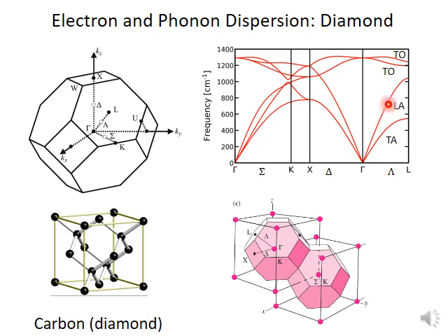Now coming to what branches there are. If you look at phonon waves which move in the 1-1-1 direction, this wave has a longitudinal acoustic branch and a transverse acoustic branch, and the transverse acoustic branch has only one branch. It would mean that the two transverse branches are degenerate. In other words, if a wave moves in the 1-1-1 direction, the transverse spring constants are exactly the same in the two transverse directions. Similarly, the optical branch has an LO branch and a TO branch. So again the two transverse branches are degenerate over here.